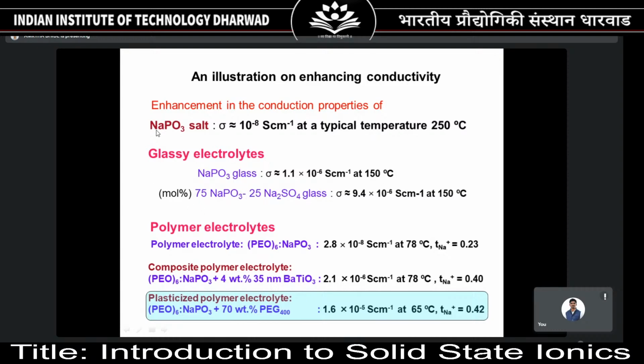When you look into the same sodium phosphate salt in semi-crystalline materials, you could see further enhancement in the conductivity. Rather, you got similar, maybe slightly higher conductivity compared to the glass, but at much lower temperature. Here we could not measure the conductivity at 150 degrees Celsius because after softening, it becomes a free-flowing liquid. We cannot measure the conductivity as such at 150 degrees Celsius, and the stability of the polymer also goes bad. That's why we cannot go up to 150 degrees Celsius. So at 78 degrees Celsius, that was the conductivity.